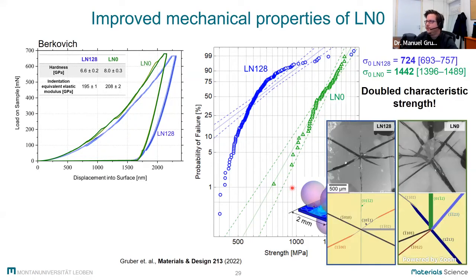And we could also see differences in the fracture behavior. So for the LN0 configurations, we do not have a cleavage plane perpendicular to the surface. So all of them have a higher angle and may be activated at higher stresses. And also due to the higher surface, the flaws and surface defects cannot be introduced so easily during grinding and polishing processes.